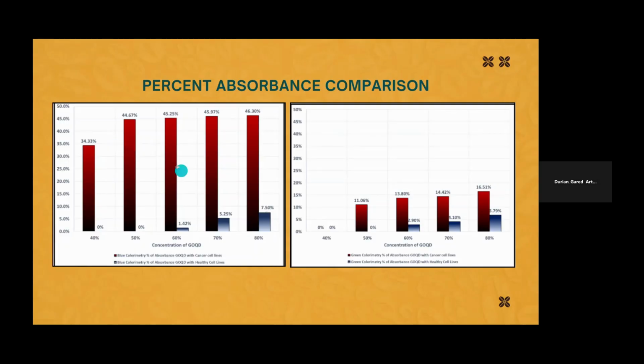Then in a dose-dependent manner, both groups display the strongest absorption peak in the blue colorimetry range, aligned with the UV spectrum, where GOQD excitation is maximized due to quantum confinement effects. This range provides sufficient photon energy to promote electron transitions and photon emissions as electrons return to their ground state. Overall, there is a notable difference in absorbance between the two groups across all three colorimetric ranges, with GOQD samples containing cancer cells consistently exhibiting higher absorbance levels, which demonstrates their potential for selective detection of cancer cells.